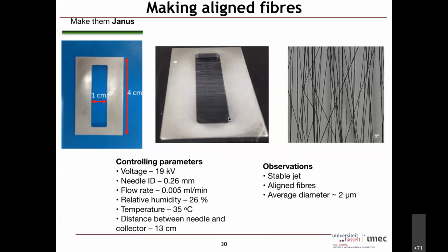This is a normal image, and if you go into the scanning electron microscope, you will see that you get more or less straight aligned fibers. Now you coat one side gold, flip it over, coat the other side with platinum. And these are all the conditions that we did.